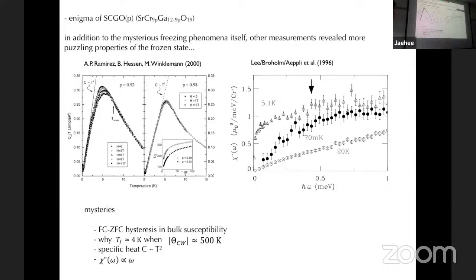So that was surprising. But then I did a neutron scattering experiment with Colin Broholm and Gary Aeppli when I was a student. And we converted the neutron scattering intensity into the imaginary part of the dynamic susceptibility, and we plot that as a function of energy. Then you can see above Tf, at 20 Kelvin, there is a gradual increase, right? So when you start decreasing temperature down to just above Tf, let's say 5.1, then this spectral weight is shifted down to low energy. That's understandable, because the relaxation becomes slower and slower.